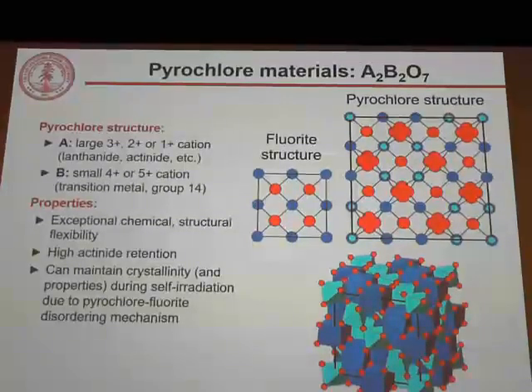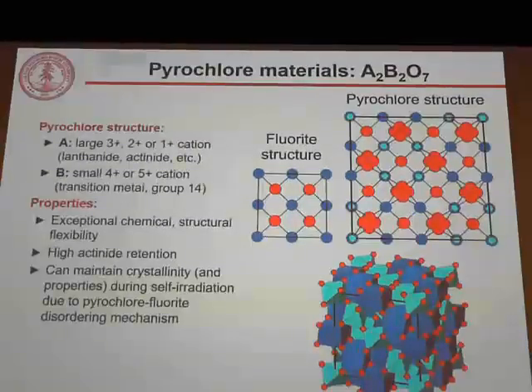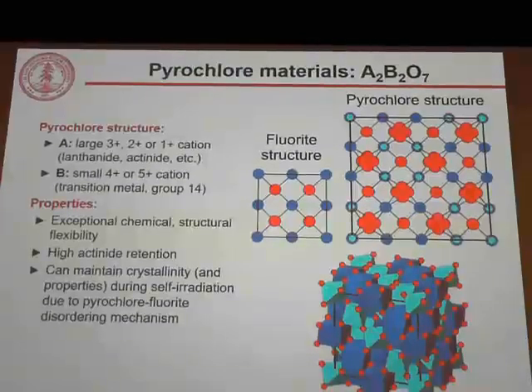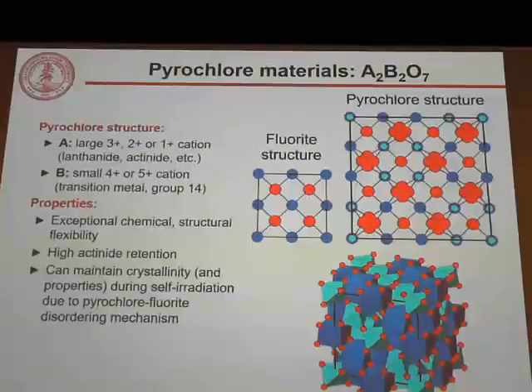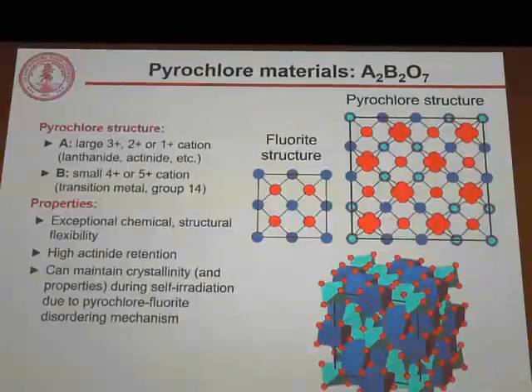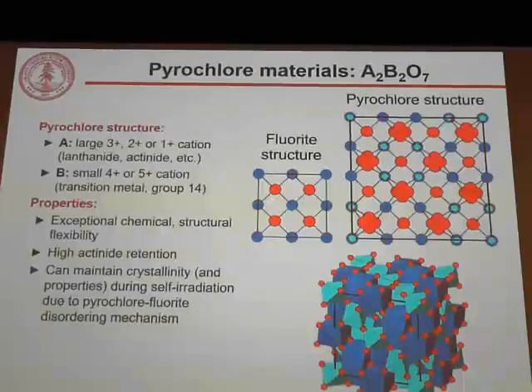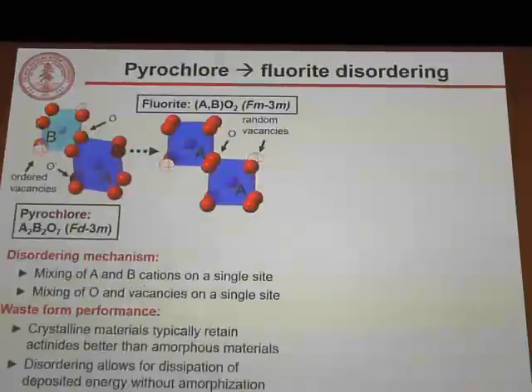They also have exceptional chemical and structural flexibility, so we can fit everything in quite nicely into a pyrochlore structure, which is based on the fluorite structure, so it incorporates things like actinides very well. Finally, they have high actinide retention due to strong bonding and coordination of the actinides. And they can often maintain their crystallinity and therefore their properties during self-irradiation, because they have access to a unique pyrochlore to fluorite disordering mechanism that allows the pyrochlore superstructure to disorder to a fluorite-like structure while still maintaining its crystallinity without becoming amorphous. So that disordering mechanism involves the mixing of the A and B site cations onto a single crystallographic site, as well as mixing of oxygen and vacancies onto a single crystallographic site, such that this pyrochlore structure becomes a disordered yet crystalline fluorite structure.